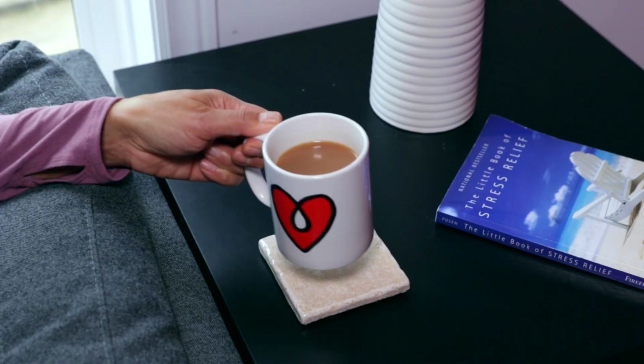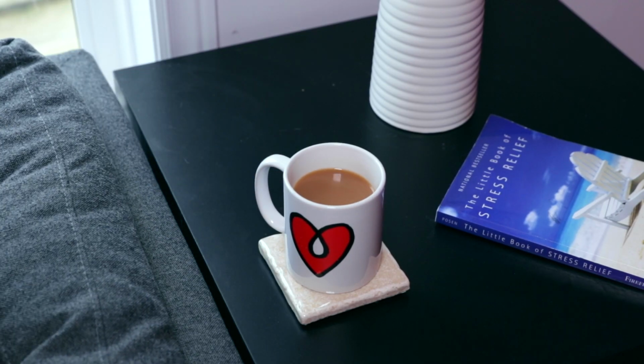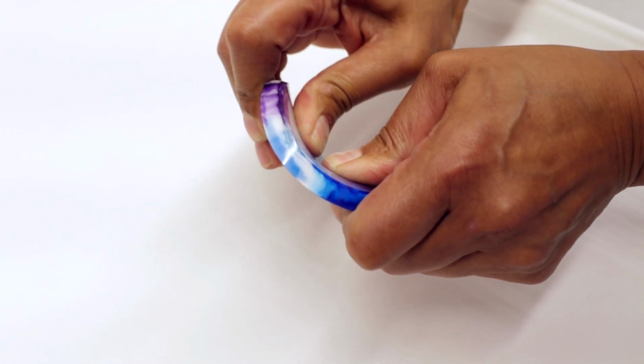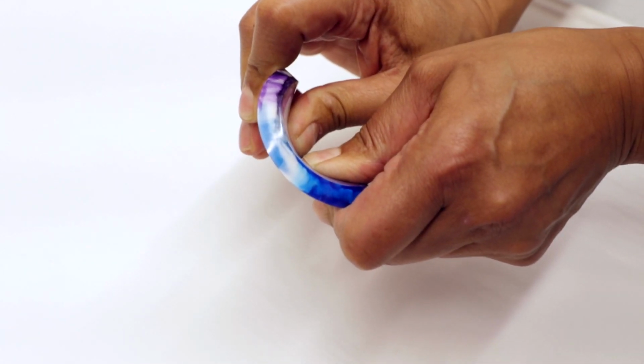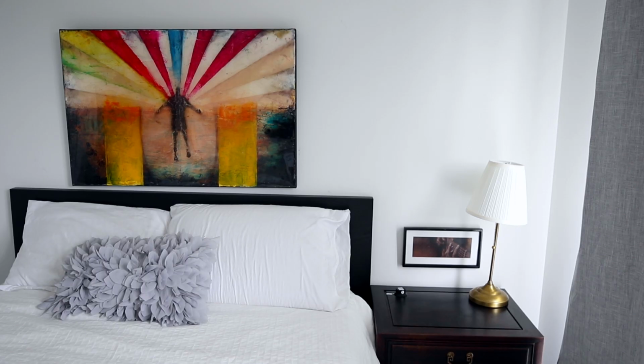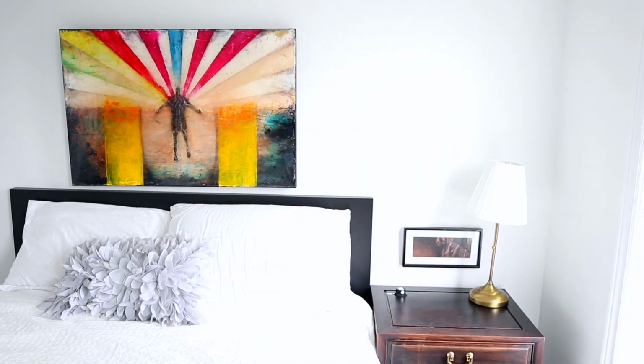Cured resin can withstand a certain amount of heat, say a warm coffee cup on a coaster, for example, but high temperatures can cause even fully cured resin to temporarily soften. The resin will quickly harden up again once it cools down, but prolonged exposure can cause the resin to shift or distort. For example, a coaster left in a sunny window may become flexible, but will harden up again once the temperature drops. In the case of resined artwork, this flexibility can make the resin vulnerable to denting and damage.